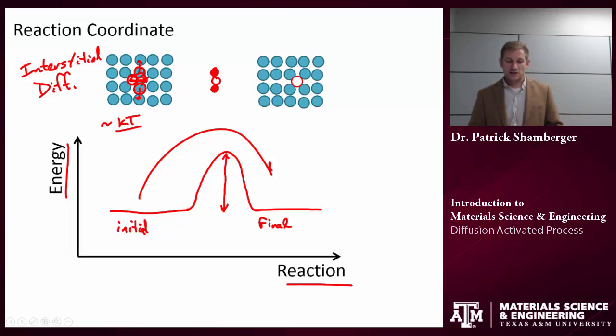The probability of this event happening is going to be exponentially proportional to the ratio of this activation energy over kT. So this term here is the activation energy. Sometimes it's also called a heat of some sort of reaction, heat of vacancy creation, heat of diffusion. You can see different variables used to describe this. But this is the magnitude of that energy barrier we have to overcome.